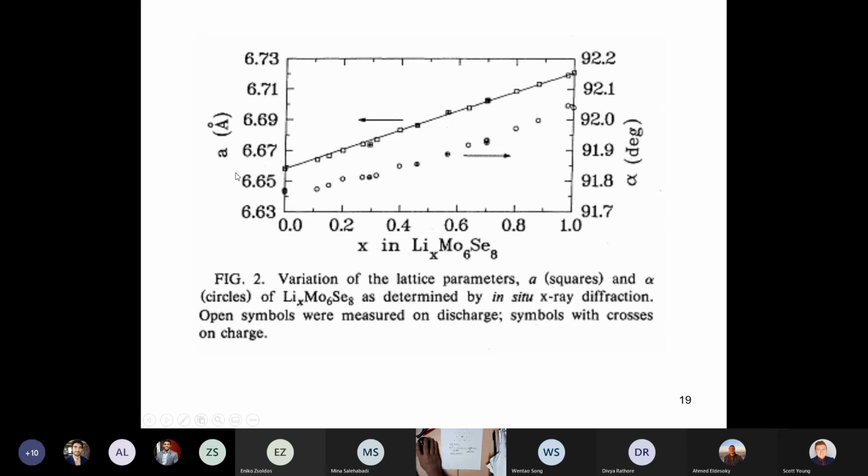The main point that you're making is the lithiums are far apart. The near neighbor distance is 6.6 angstroms. In addition, this material is superconducting. So the density of free electrons is incredibly high. So the screening is really, really good.